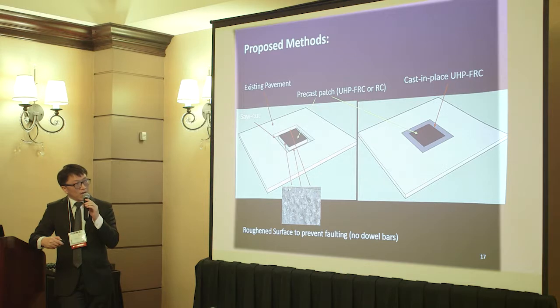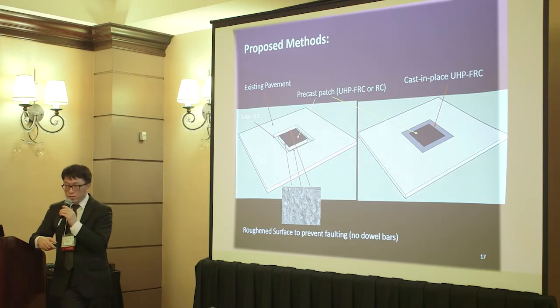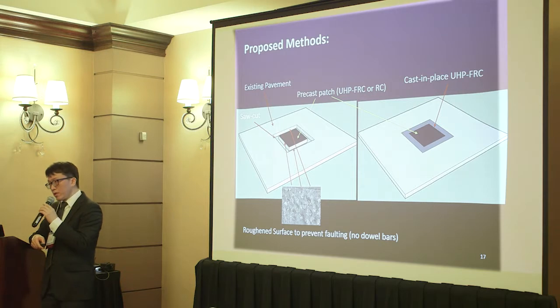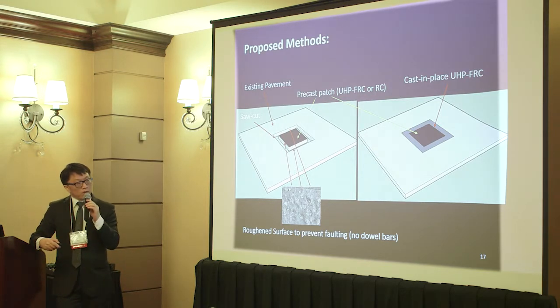So on site, the casting work for UHP-FRC is very minimal. You put a patch here and then cast UHPC on site, probably 2 inches is enough. It depends on how fast you want the strength to grow. If you want, for example, to reach 2,500 PSI in 4 hours, you may need some on-site curing here to get that strength quickly.